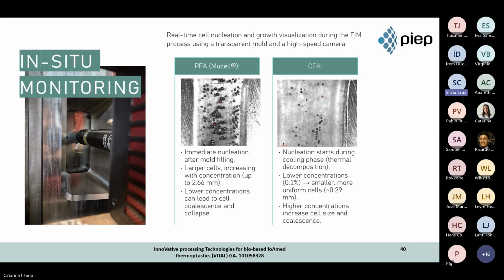When working with bio-based polymers, we often face narrow processing windows and thermal limitations. So mold sensorization and in situ monitorization make it possible to better understand how material behaves during expansion, helping us define strategies to stabilize the cell structure and ensure adequate mechanical properties.